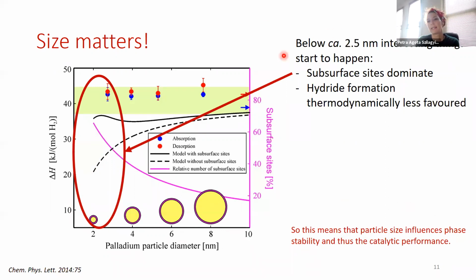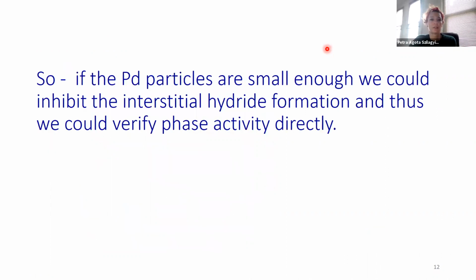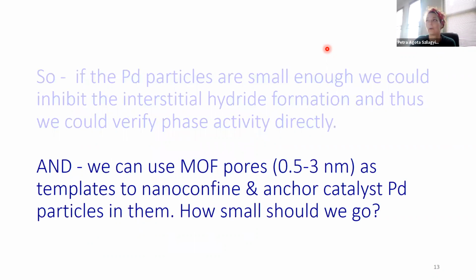And one more thing I'd like to point out, that all these different behaviors occur or start to occur below 2.5 nanometers. And once again, I would just like to remind you that this is really much the pore size regime of metal organic frameworks. So if the palladium particles are small enough, then we could inhibit the interstitial hydride formation. And so we could verify the phase activity directly. So whether it's the hydride phase that is indeed the more active and less selective, or perhaps the other way around. And also, of course, we can use MOFs as templates to nanoconfine and anchor catalyst palladium particles in them.